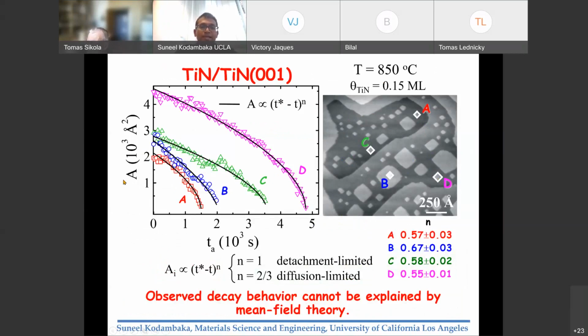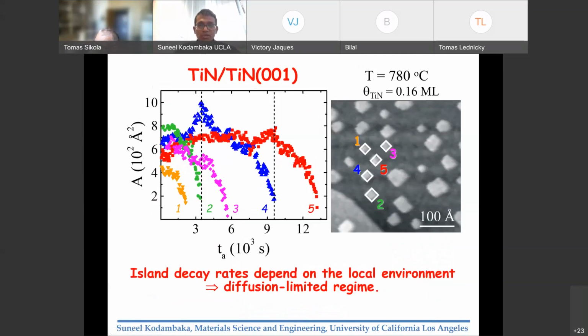And we can plot the area as a function of the annealing time. And as you can see, for the 4 of these curves, we can use the power law relation, using which we obtain scaling exponents anywhere between 0.55 and 0.67. These are close to 2/3, but not exactly the same as what is expected from the mean field theory model. Okay. And so to explain this quantitatively, we have to do additional experiments or observations.